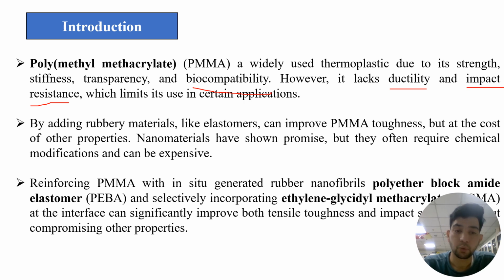So we can improve this property by adding a rubbery material, like an elastomer, which will improve toughness, but the other properties will be lost. But in this paper the author added an elastomer, PEBA, and also a compatibilizer, and the interesting thing was that it improved one property and the other properties were not reduced. That is the good point. So reinforcing PMMA with in situ generated rubber nanofibrils polyether block amide elastomer and selectively incorporating ethylene glycidyl methacrylate at the interface can significantly improve both tensile toughness and impact strength without compromising other properties.